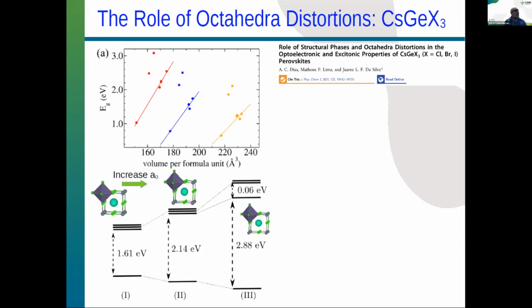To understand what is responsible for this effect, because when you change the structure, we also find that there's a change in the volume, an increase in the volume in that particular case. And then what we did, we picked up the ideal structure and calculated it at the same volume as the last one.